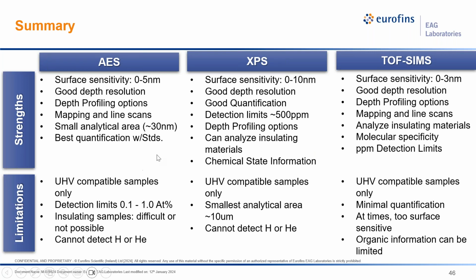Auger gives us the best analytical area of about 30 nanometers. ToF-SIMS gives us the best sensitivity for parts per million, parts per billion detection limits. XPS gives us the most chemical bonding information. ToF-SIMS the most chemical specificity. Limitations are all similar for the techniques.